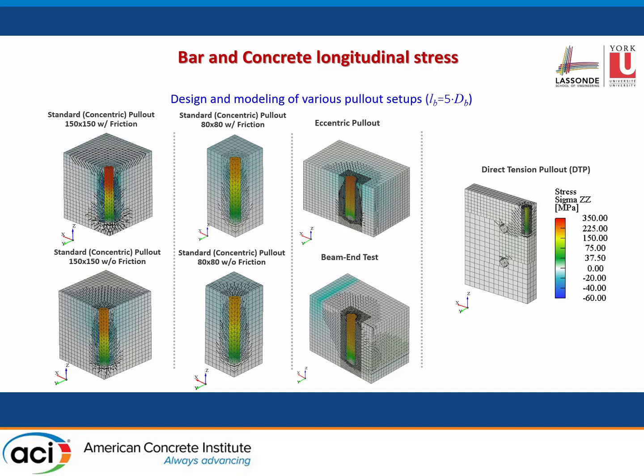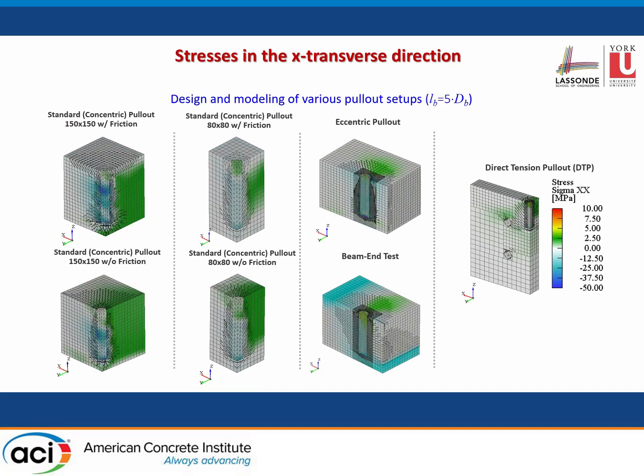So this illustrates the effect that the specimen form has on the bond slip law that you will read. And this continues on to illustrate the effect of the transverse confining pressures that are acting on the bar. And again, you see very great differences depending on the specimen form.